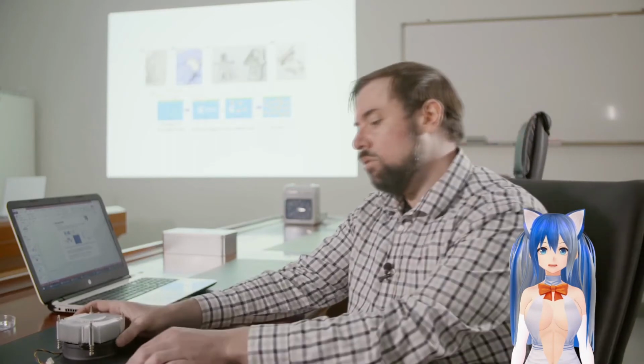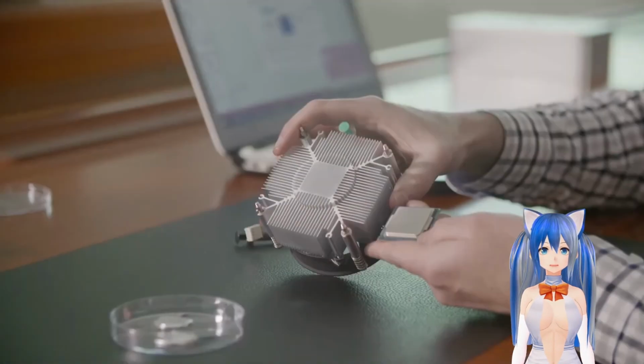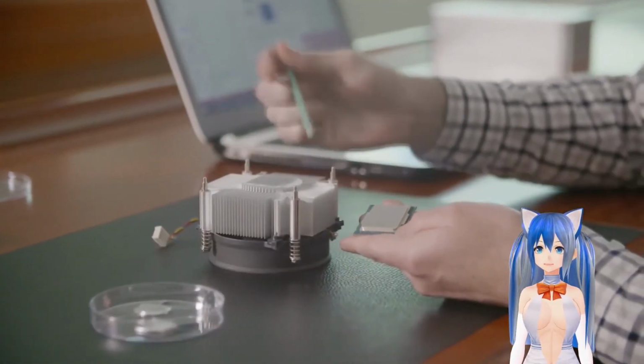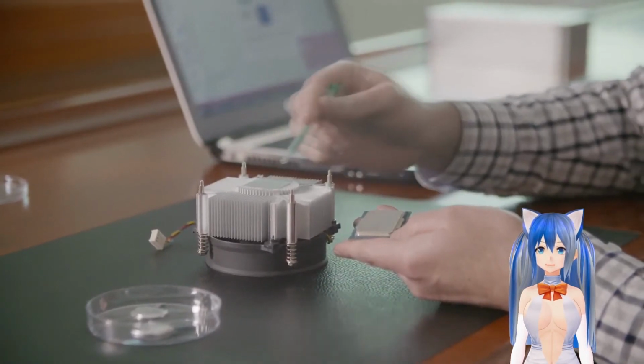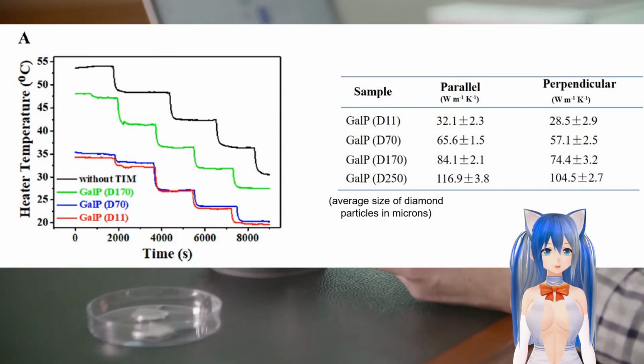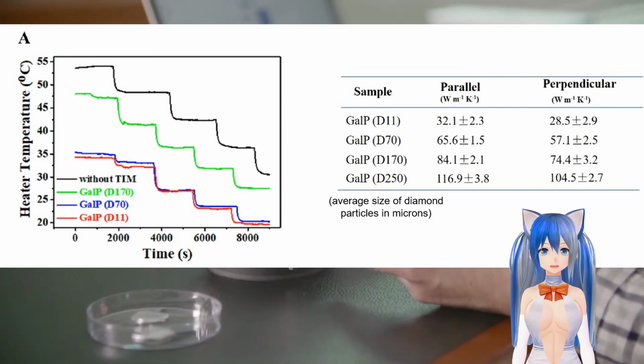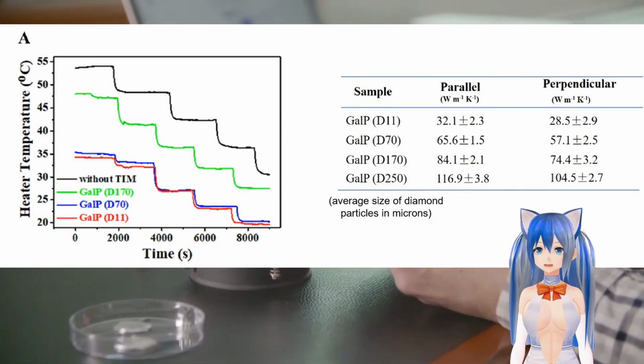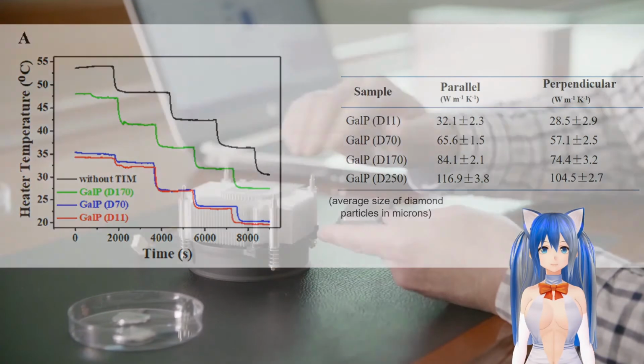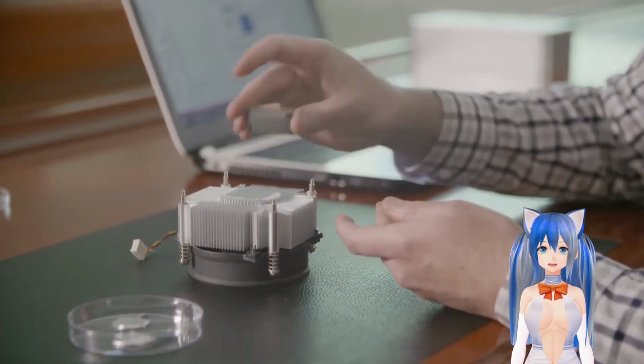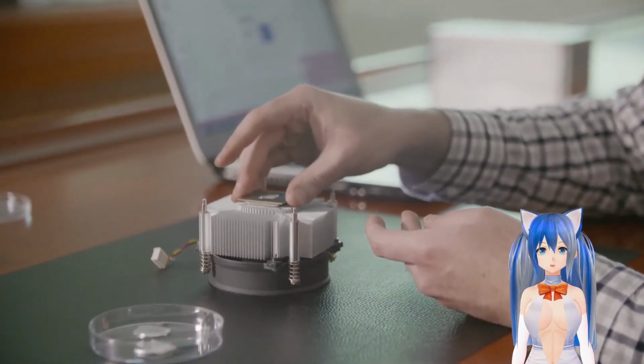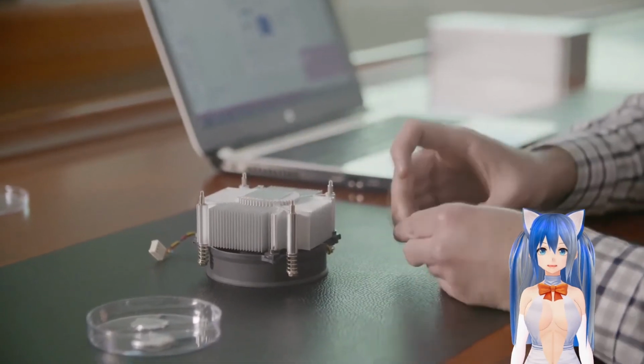The application experiment further proved the gallium-diamond mixture's effectiveness as a thermal interface material between a heat sink and a heat source. Interestingly, the composite with smaller-sized diamond particles showed superior real-world cooling capability despite having lower thermal conductivity. The reason for this discrepancy is due to the larger diamond particles being more prone to protruding through the bulk gallium and creating air gaps at the interface between the heat sink and heat source, reducing its effectiveness. The researchers note that there may be some ways to solve this issue in the future to further improve the performance.